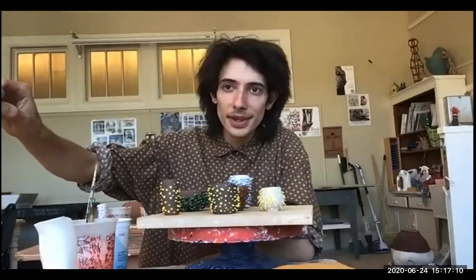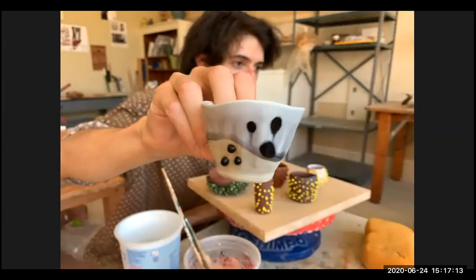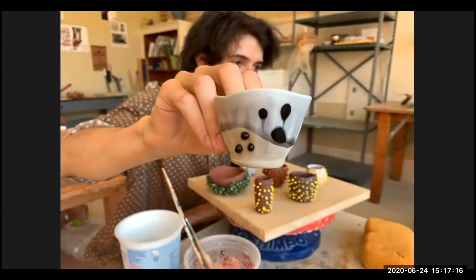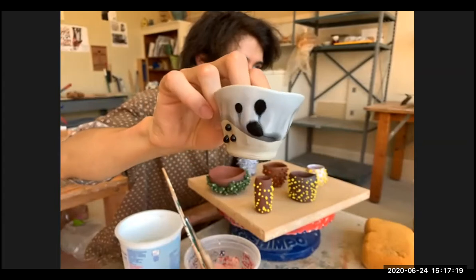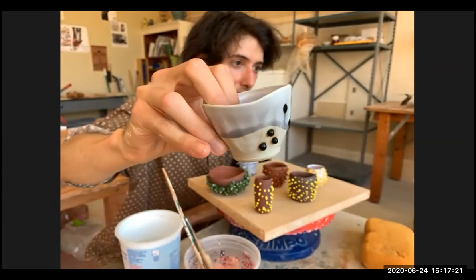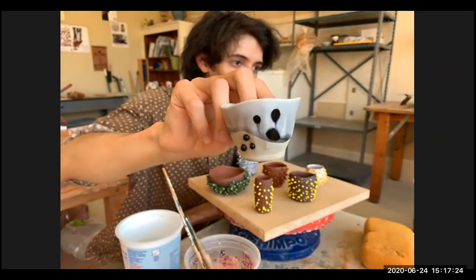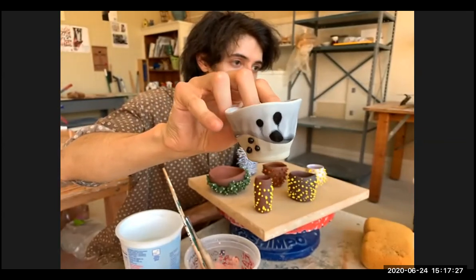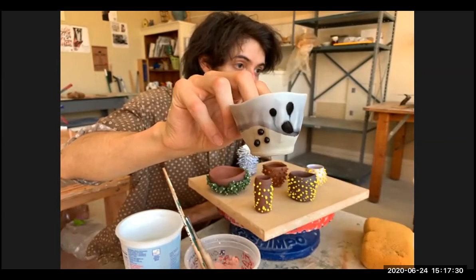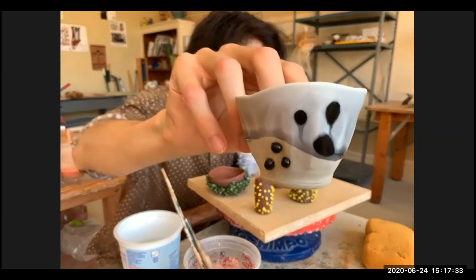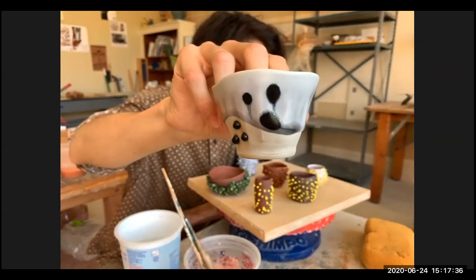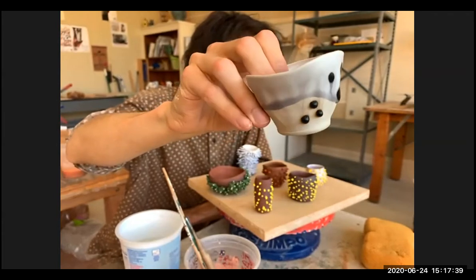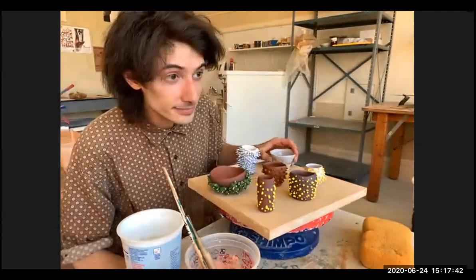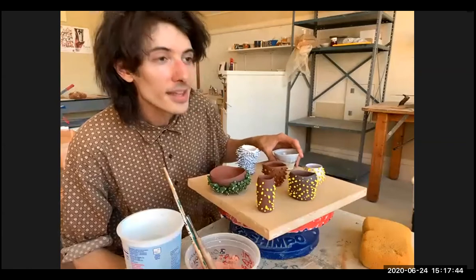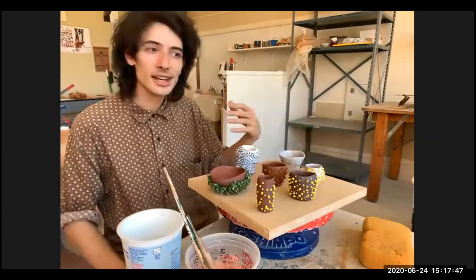Oh, this is actually kind of out of left field as well. Here, you can see the difference between these blobs on a clay surface on the bottom, where they're not really melting; they're just maintaining their droplet form, and then on a glass surface where they diffuse into the liquid glass and sort of run, bleed out a little bit. So it's the same material, it's just one of them goes on a glassy surface and one not? Yeah, just an interaction.